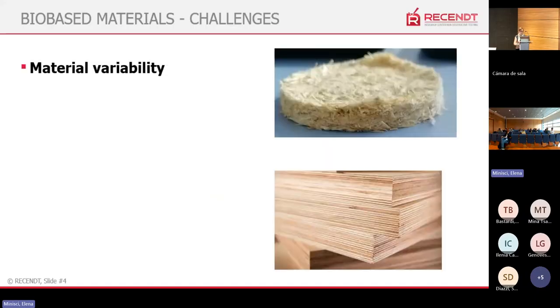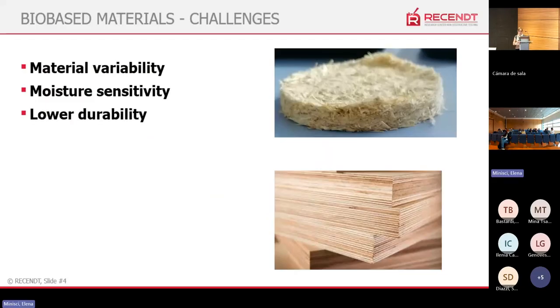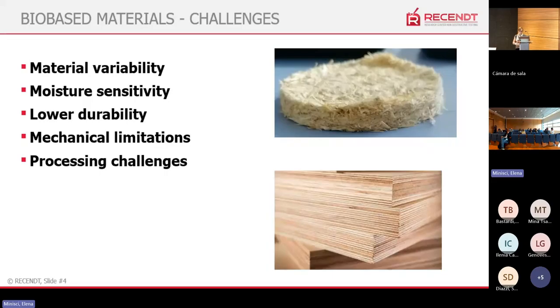Valentina gave us a good overview about bio-based materials, so I can make it short. Many bio-based materials have their challenges in their structure, in how they build up with fibers, different fillers, and combinations, and they are sensitive to moisture uptake. This also makes for lower durability, has an impact on their lifetime and on their mechanical properties, and sets limitations for bio-based materials. They are sometimes not easy to produce, and the processing of the materials is also challenging.